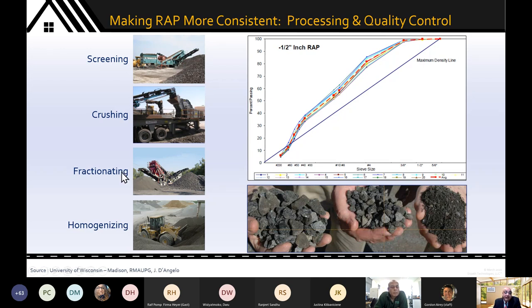Finally, you've done that, you've fractionated it, and this is perhaps one of the most important steps. You take your RAP pile, and using an earth mover, you turn it over a couple of times, because I think everybody in this room recognizes that if you walked into a freshly milled RAP pile, pulled a sample from one region and analyzed it, you may get an entirely different result than if you pulled a sample from the same pile from a different region. And that is the reason you want to homogenize this pile, so as to have a very consistent incoming material.